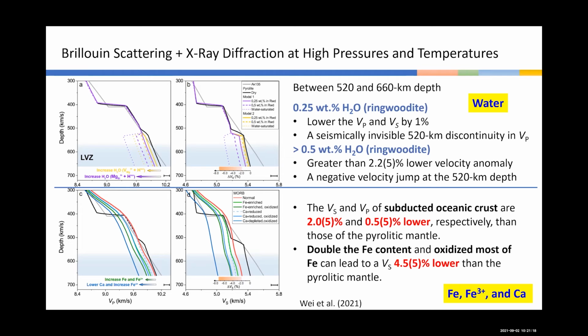So let's go back to the seismic observation. The seismic observation shows more than 2%, 2 to 7.4% reduction in the shear wave at the bottom of the transition zone. So that means we show here that if water is only present as hydroxyl in mantle minerals, it will be very difficult to explain those velocity anomalies. Another opportunity is that the low velocity anomaly at the bottom of the transition zone is caused by the accumulation of the subducted oceanic crust.